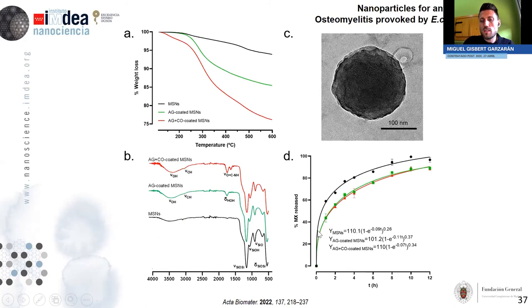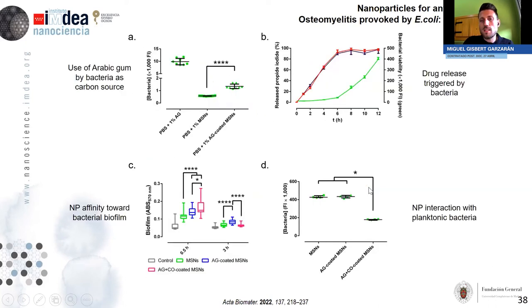a small difference between the non-coated and the coated with Arabic gum nanoparticles in the release. But in this case, the release is the same. So that means that the coating of the nanoparticles is being degraded by bacteria. And here is the experiment that I was talking about previously.